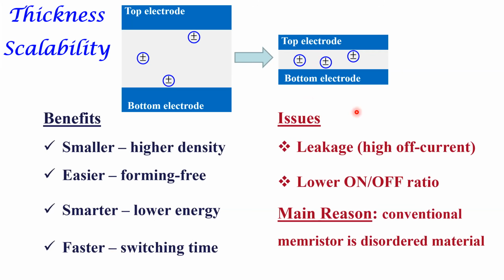However, there's been challenges that have prevented this scaling, at least in metal oxides. These challenges include the fact that as you make them smaller, these defects, the native defects in the material, for example in many oxides, begin to form a short between the top and bottom electrode. So that leads to very high leakage current, lower on-off ratio.